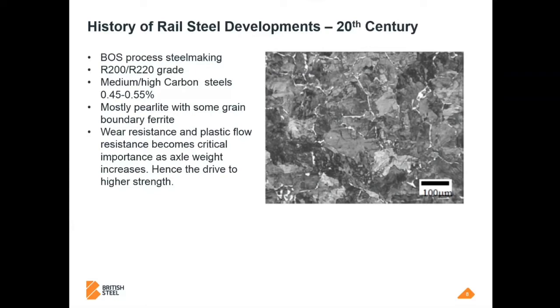So we have to introduce some methodology to control the hydrogen, which initially was just ingot slow cooling. They would cast the ingots and then stack them all up in a pile and put like a refractory lined shed over the top of them just to slow cool them and allow that hydrogen to diffuse out. Nowadays, we have slightly more modern methods, vacuum degassing, but we'll come on to that.